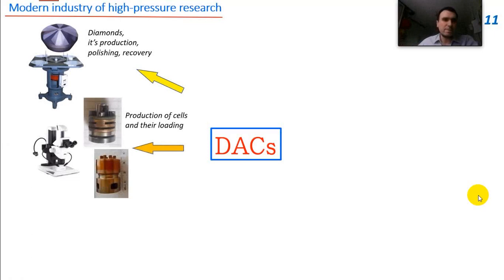for diamond anvils actually. The next stage is you need to find a factory which will produce diamond anvil cells. Exactly, the metallic part, the piston and cylinder of diamond anvil cells. It's a very complex process, and we ordered it in Fab Lab Skoltech about 1 year ago, to produce several cells, and the quality was not so good. So we decided not to work with Fab Lab Skoltech anymore, and it's really better to purchase such cells, but they are quite expensive. Each cell costs about 5,000 euro.